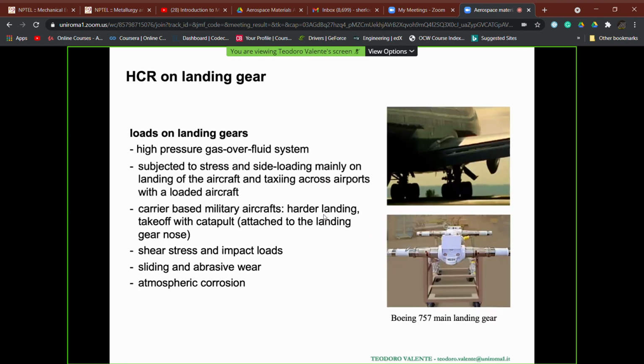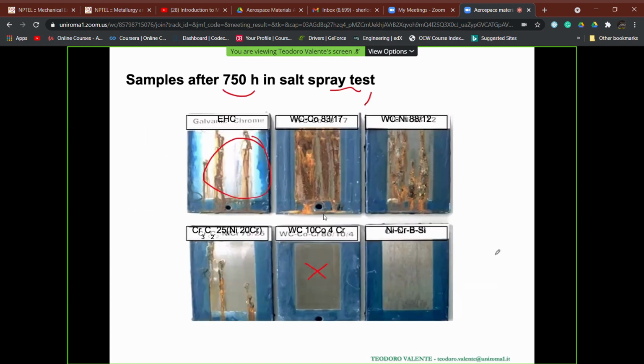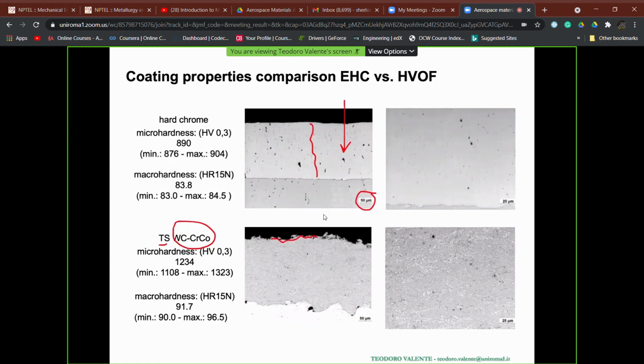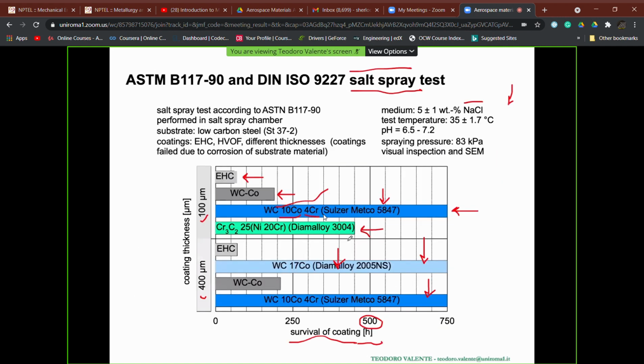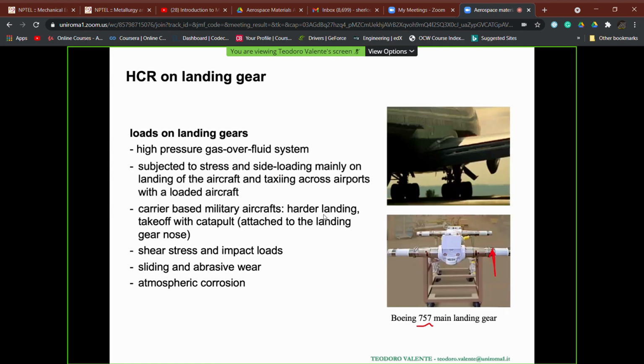Other examples of parts which have been coated. This is a 757 main landing gear by HVOF. You see the silver appearance here of the parts which have been coated. Obviously, this is due to the roughness of the thermally sprayed coatings after fabrication, so we need to machine the surface in order to reduce roughness and also, in this case, the silver appearance.